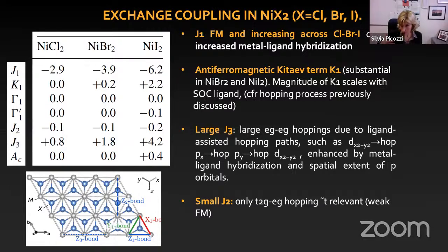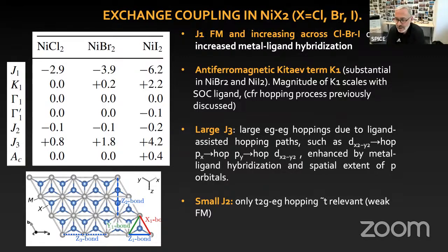So what I believe is a really typical characteristic of NiI2 is that it has this strong anisotropic exchange at first nearest neighbor, but it also has a strong antiferromagnetic J3, which also frustrates this lattice. So it's not only the anisotropic exchange, also the J3 is instrumental to getting this complex spin texture. So yeah, the answer is we tried, but we failed. Just the d8 seems to have a large anisotropic exchange. The others we tried are small. Maybe iron or cobalt have larger anisotropic exchange, but we didn't look at it because they have additional effects that one should consider.